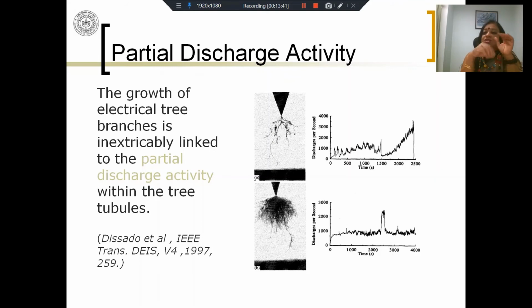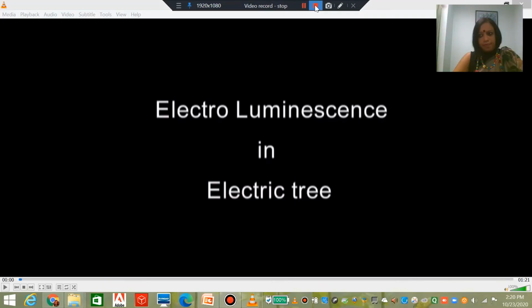The first thing it does is it causes the tree to continue to grow, and if considerable growth happens towards the other electrode, ultimately complete failure might happen. Otherwise also, it continues to cause damage to the channel walls, and degradation may spread horizontally. So this video was created in my lab where we were filming a tree in an epoxy resin sample. We had a needle plate electrode, and the tree had already progressed to a certain extent. There were some filamentary channels created, and we were able to see partial discharges actually taking place inside the tree channels, and the channels growing larger, thicker, and broader.